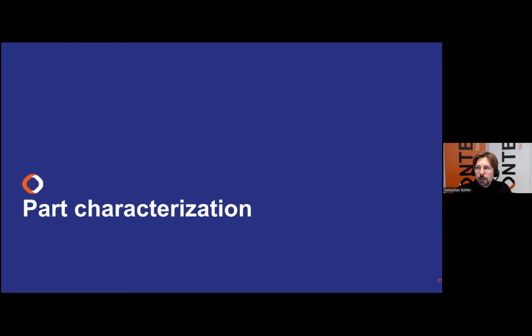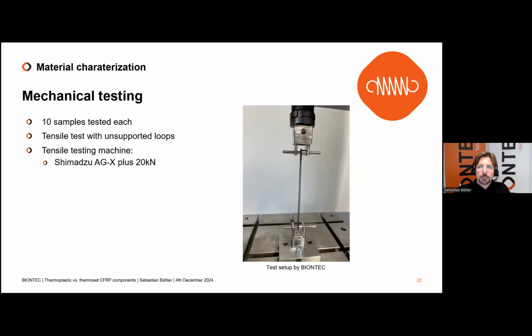Last but not least, I would like to give you an impression of the part characterization and the behavior of the thermoset continuous fibers and the commingled fibers, stapled yarn. Therefore, we used our in-house testing machine. We tested 10 samples each for the thermoplastic route and the thermoset route. The tensile test has a non-supported loop above here. And the tensile testing machine was the Shimadzu AG-X plus 20 kilonewton, and the test lab is here in St. Gallen.